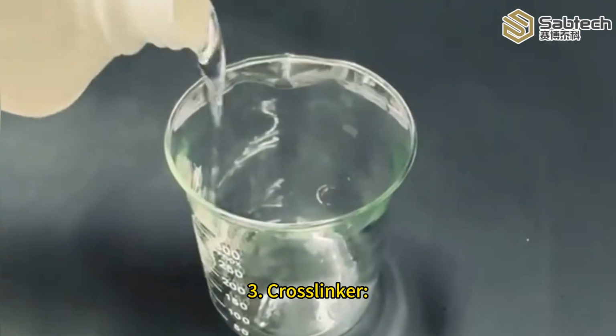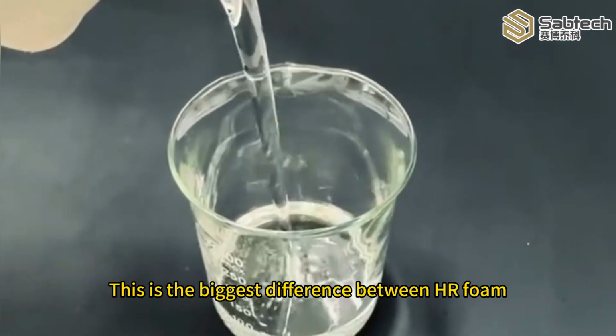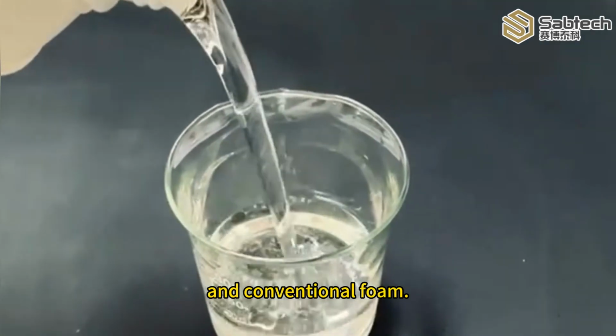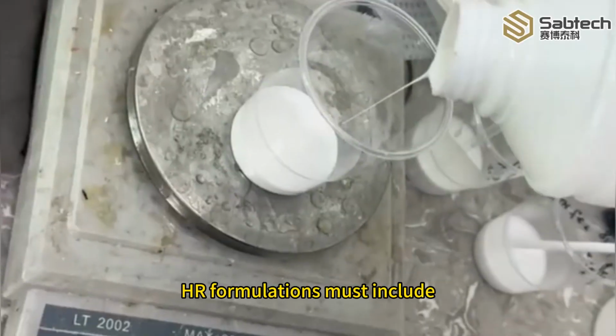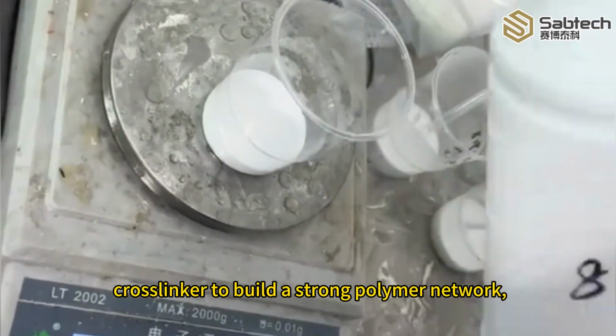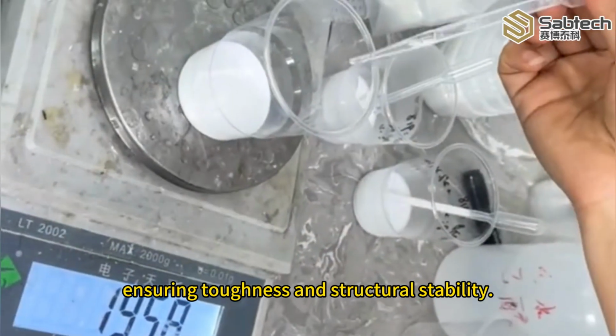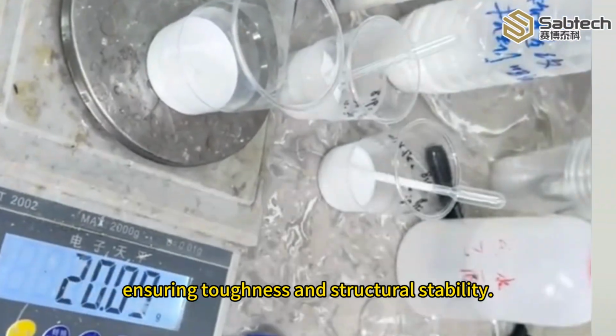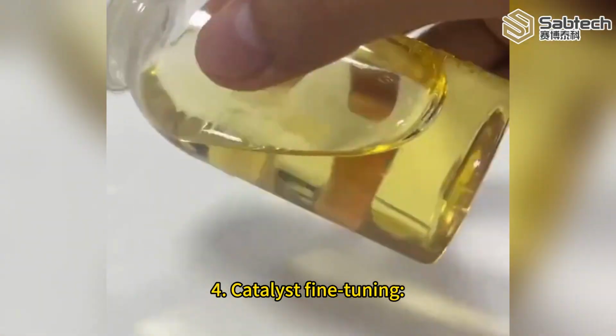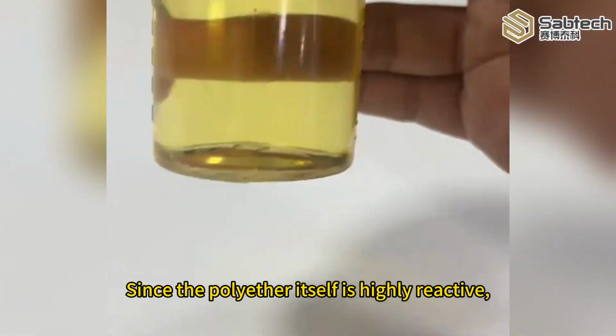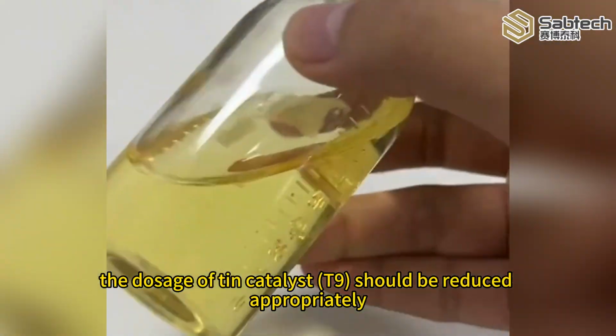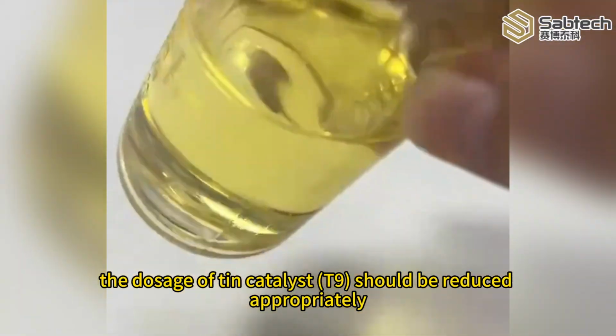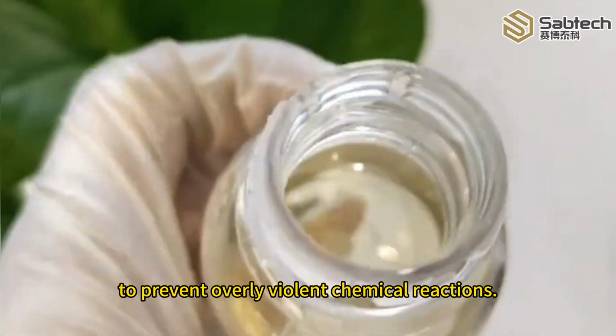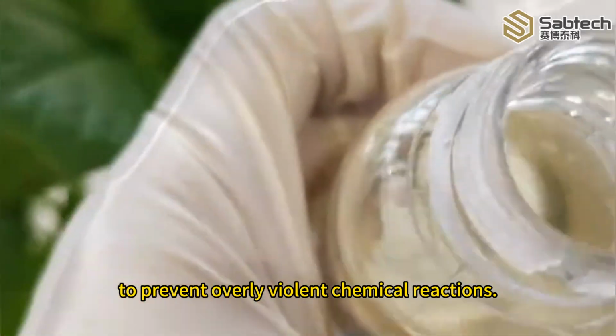3. Crosslinker. This is the biggest difference between HR foam and conventional foam. HR formulations must include a crosslinker to build a strong polymer network, ensuring toughness and structural stability. 4. Catalyst fine-tuning. Since the polyether itself is highly reactive, the dosage of tin catalyst, T9, should be reduced appropriately to prevent overly violent chemical reactions.